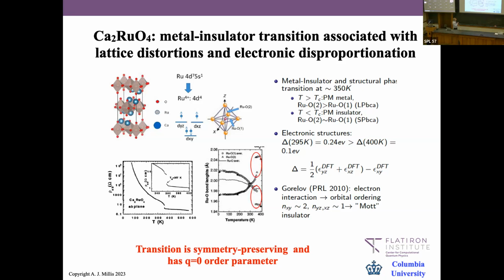In particular, the basic unit of this material is a ruthenium oxygen octahedron, shown here. When you go through the transition, the octahedron flattens. So that's a structural change. For those of you who like these things, it's symmetry preserving, same structure on both sides, but just different atomic positions. And associated with that, there is a change in the occupancy of some of the ruthenium orbitals.